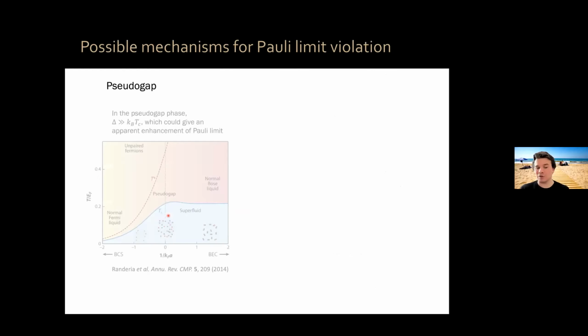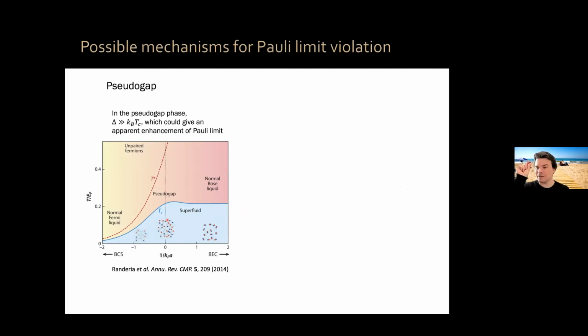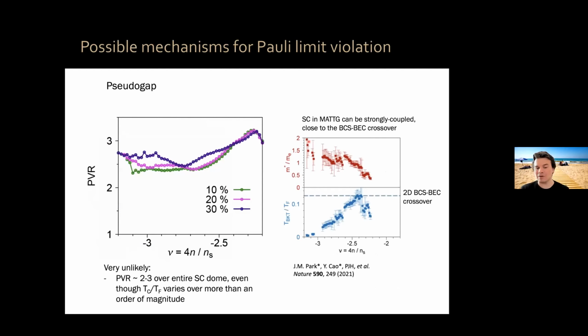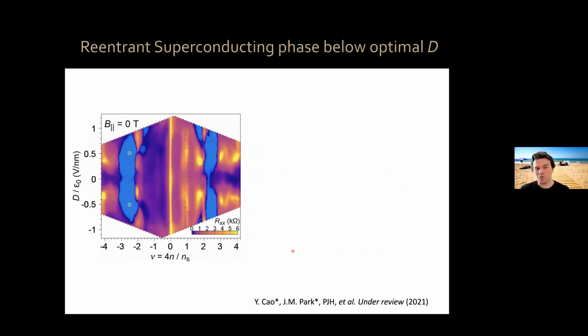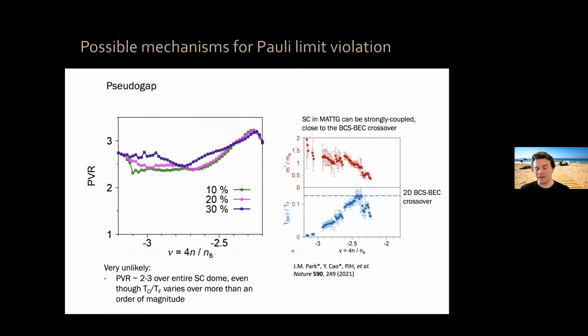Another possibility is that because we're in the strong coupling regime, we have a pseudogap where the amplitude pairing has nothing to do with TC. TC is determined by the superfluid density or the phase stiffness. But we see that this violation of the Pauli limit is present everywhere in the entire superconducting dome, even though the coupling strength can vary by over an order of magnitude. So it is very unlikely that any of those mechanisms explains our data, and therefore it's very unlikely that our Cooper pairs are spin singlets.